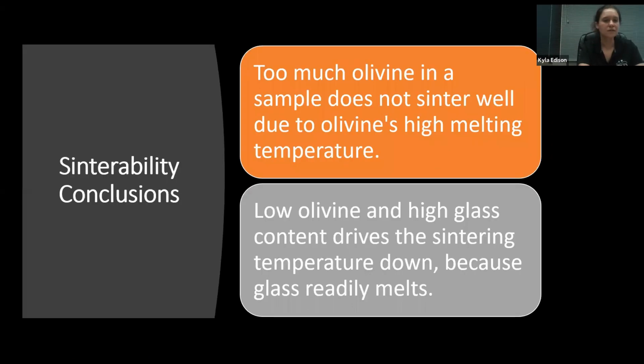And so my conclusions to this, again: too much olivine in a sample does not sinter well. A low olivine and high glass content actually drives the sintering temperature down, which is also maybe beneficial. With these highly glassy materials, I was able to drop the temperature down, which could possibly save on energy. But like I said before, the quarry 1 and quarry 3 materials are probably the best that I have, and they tend to be the most durable.